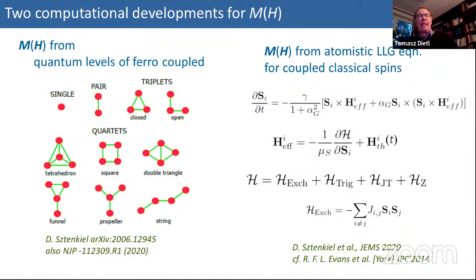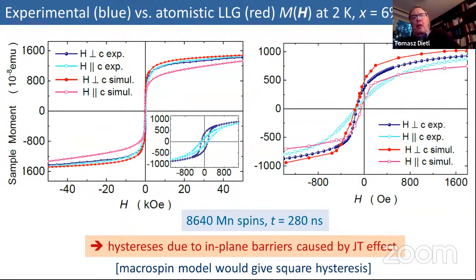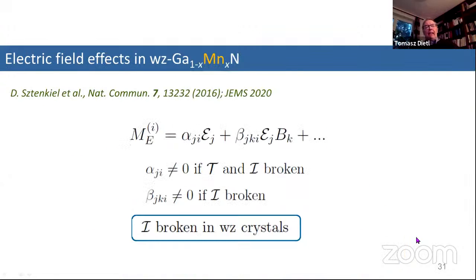And the results of this calculation compared to magnetization are shown here. It was done for almost 10,000 spins. To see this equilibration, you need 280 nanoseconds. Red is simulation, blue are experimental data. And you see that you can describe this half of the hysteresis not so badly, hysteresis for this easy and hard axis in this gallium manganese nitride. So you have a tool to describe an interacting system not by macrospin, but by local spins, but it's a classical approach.